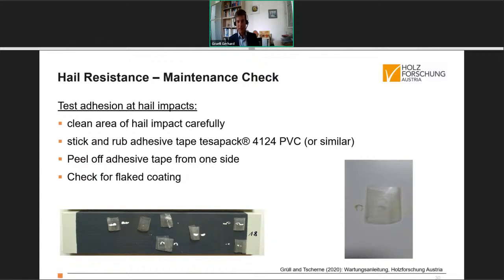The reason why we bring forward this method for practical use is that we found out in our research that the tolerance of coating systems is different for weathering after the hail impacts until the adhesion gets lost. As I've shown you with just 2 examples from our research in the slides earlier, there can be up to 12-month tolerance of a coating system, so that it's still possible to repair it with a simple maintenance coat because adhesion around the hail impacts is still good. It may be with some systems that some weeks or just 1 month after the hail impact, adhesion is lost. But we've seen a few high-quality systems where adhesion was good after 6 months, 5 months, up to 12 months natural weathering after the hail impact occurred.